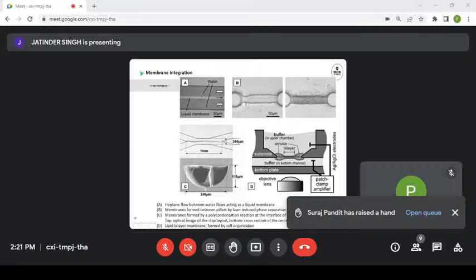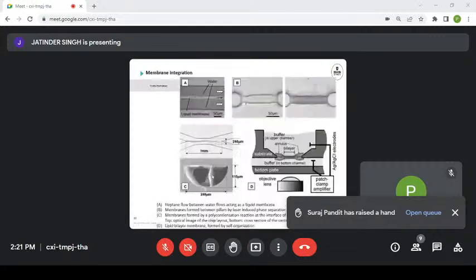One of the nice things I like about this picture is that they haven't quite balanced out the flows. You can see that the fluidic resistance here was a little bit lower than it was here, or this pump was working a little bit harder. And you can see that the interface was shifted a little bit, and because of that, our membrane is shifted a little bit as well.